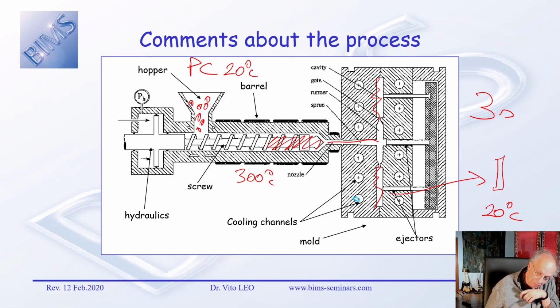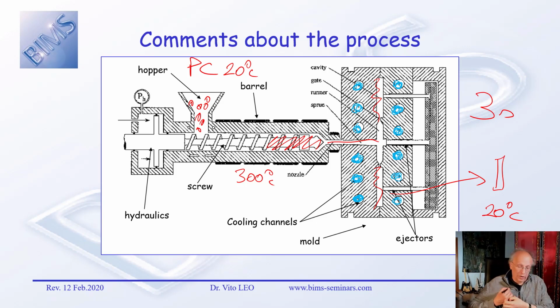Well, because these are cooling lines, so the molds are cold. Now, they might be hotter than room temperature, but they're still very cold compared to the melting temperature or the softening point. If this is polycarbonate, the mold might be 60 degrees. But polycarbonate solidifies at 140 degrees roughly. That's the Tg of polycarbonate. So we do something crazy, really. We try to fill a cold mold.